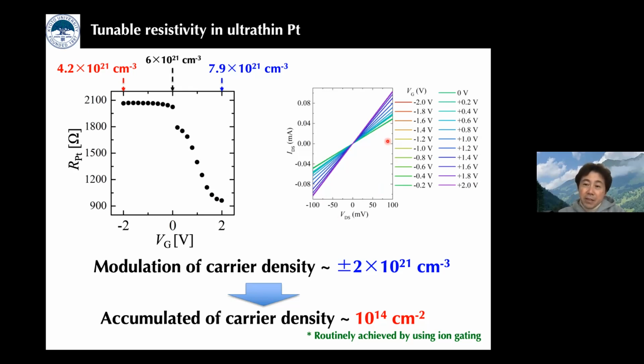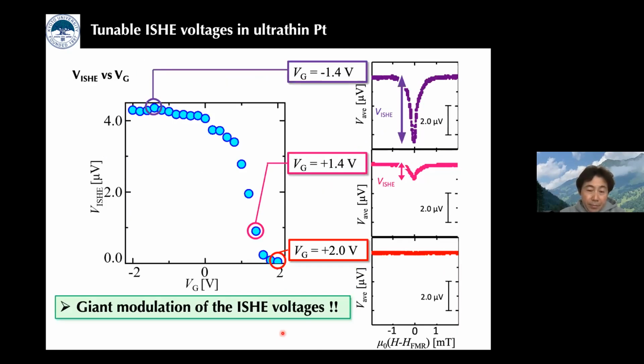but we control the resistivity of platinum itself. We can also estimate the accumulated carrier density to be 10 to the 14th per square centimeter. Of course, this is a very large value, but at the same time, I emphasize that such dense carrier accumulation can be routinely achieved by using the ionic gating technique.